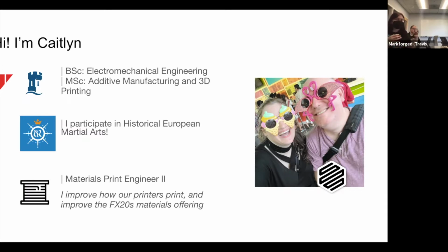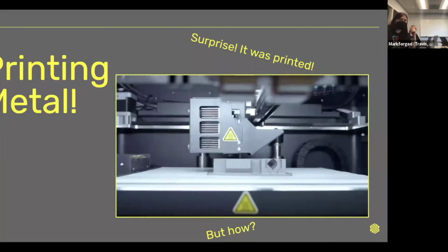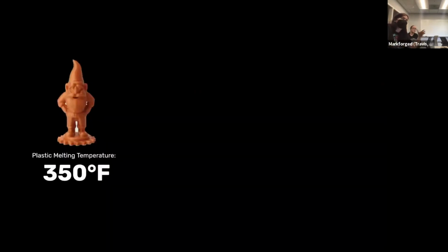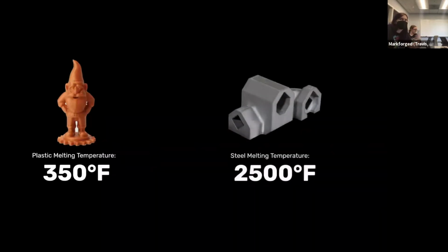I'm mostly focused on composites, but I'm going to be talking about our metal system today. So how do you go about printing metal? Some of the biggest issues with printing metal in an FFF system is the plastic melting temperature. Even higher temperature thermoplastics are usually around 350 F, and that's acceptable for the technology. But when you're looking at metal melting temperatures, steel melting temperature is 2500 F. If you try to go much higher than 350, you can't do it. How do you manage to print a part in a material that has a melting temperature of 2500?